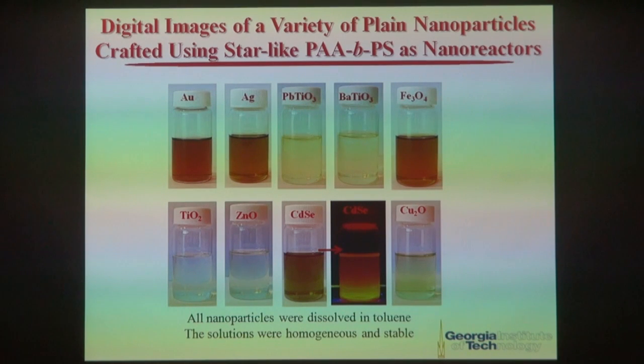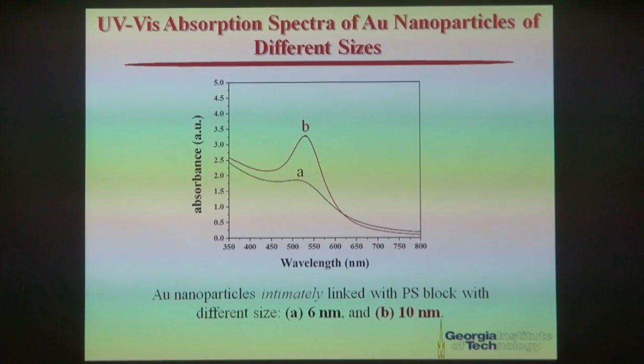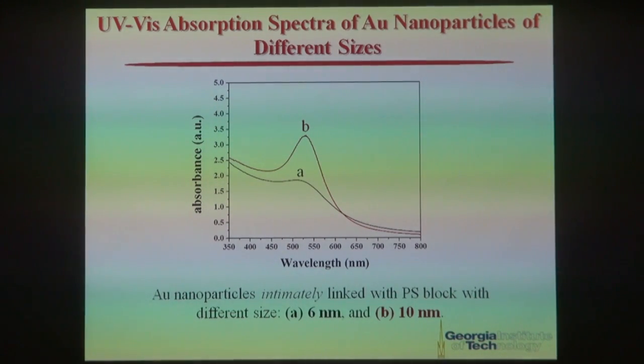The solubility of this nanoparticle actually is also very good, as the surface of the nanoparticle is intrinsically, permanently capped by polystyrene chains that is originally covalently connected to the inner PAA block. So here you see all these nanoparticles, they are dissolved in toluene, and we are talking about very good long-term stability. More than 2 years, we don't see any precipitation from the solution.